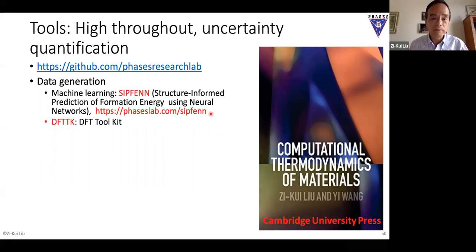So we can try this new network. And the accuracy, I think, is around 40 meV so far. So it's 4 kilojoules. So it's not too bad. It's probably comparable with calorimetry measurements. And then we also have the DFT case with high throughput DFT calculations. If you want to do some DFT calculations, you can make them temperature dependent with the Debye model or another model, you can get its code. It's again on this website.